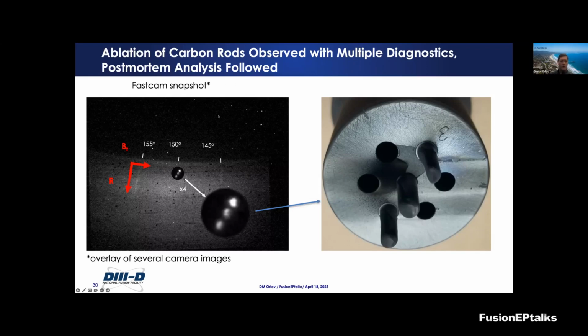This is one of the discharges, and the picture on the left is what we could see with the fast visible imaging camera looking vertically at DIMES. The DIMES port is located here. This is a zoomed view with the 3 rods that you can see here. One of them is getting the highest heat flux and shows up as the brightest white spot on the visible imaging. This is that rod that I was showing earlier, the one that ablated the most.